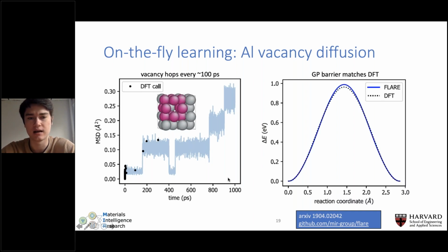And to check the energetics, we can compare against our ground truth, which for us is DFT. Here we're looking at the energy barrier of vacancy migration. The blue line is the prediction of the GP, dotted is DFT, and you can see there's very good overlap. So we can trust the dynamics that are predicted by the model.